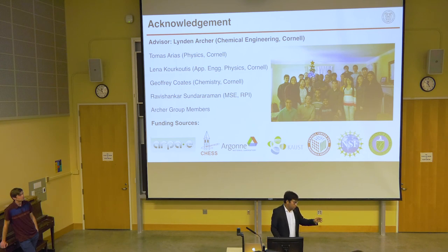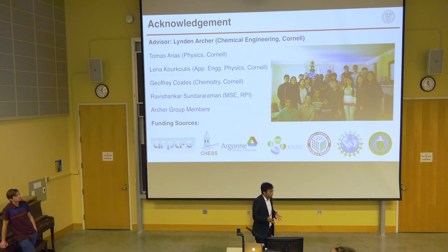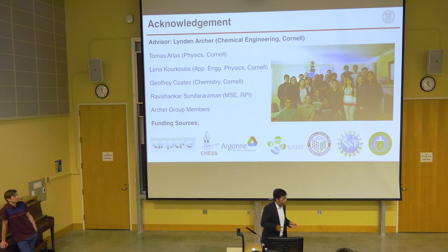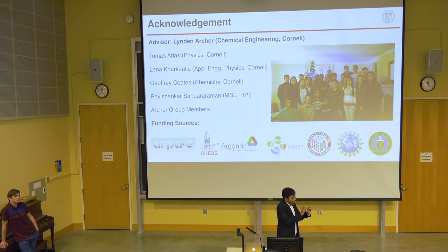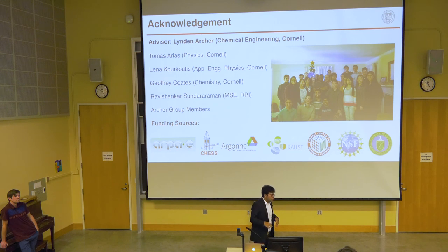Talking about the second question, about the membrane, yes, you're absolutely right. In fact, we are currently working on a cross-linked PEO membrane, where we cross-link the polymer chains using UV light, with methacrylate groups that cross-link to form a membrane. You can calculate the effective pore size by doing DMA to look at the modulus. That can work in a very similar way to the cross-linked hairy nanoparticles. I chose the cross-linked hairy nanoparticles because I wanted to systematically change the pore size, which was much easier with nanoparticles, but it can definitely be done with any other kind of material.